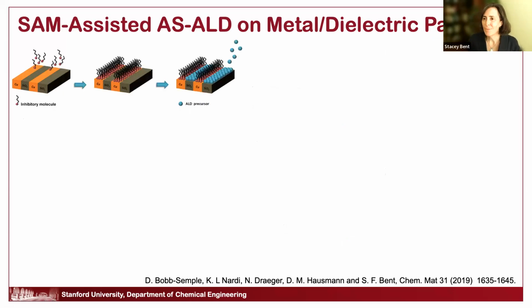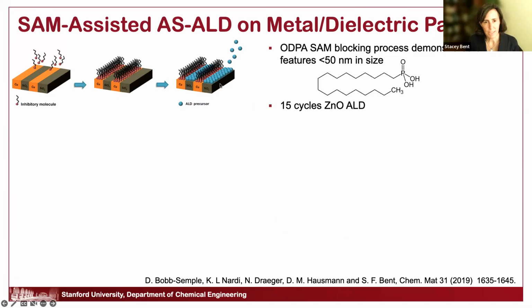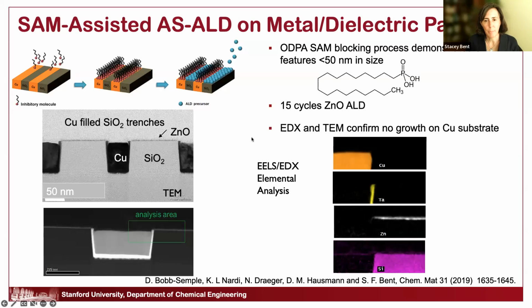Now, fast forward 15 years, and there's a lot more interest currently on looking at back end of line. So here we'd be interested, for example, in doing this dielectric on dielectric, this DOD, where we would preferentially block the metal and get growth only on the dielectric. And I'm showing an example here of SiO2, but we and other groups have also looked at doing this on low-K dielectrics. So here's the kind of molecule we use as the inhibitor. It goes down preferentially on the copper, and these are the results of a process using that.